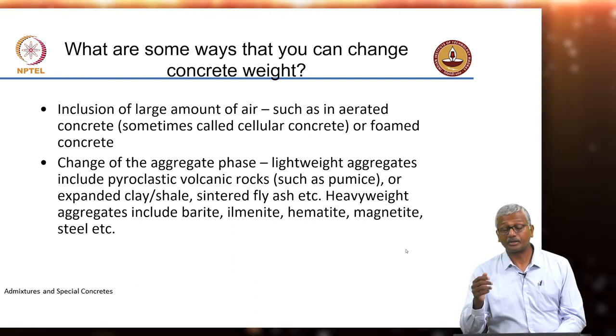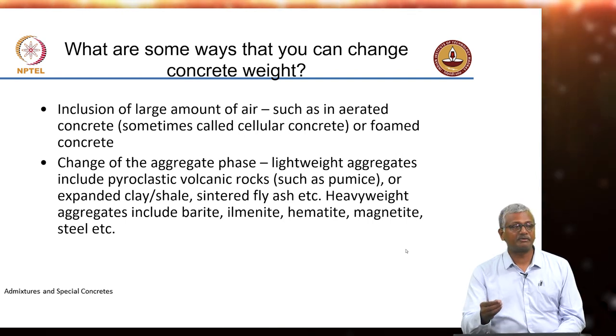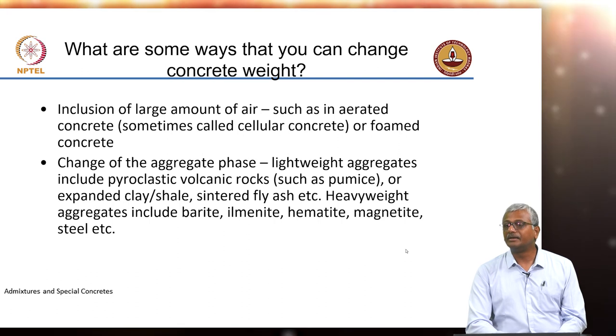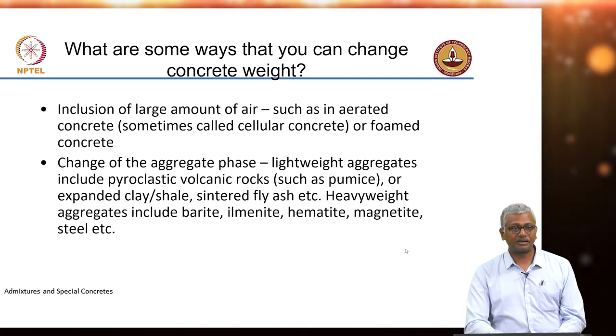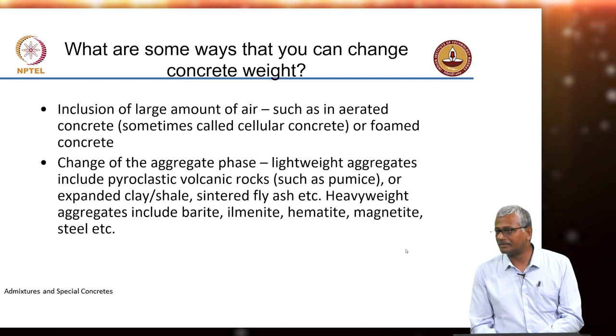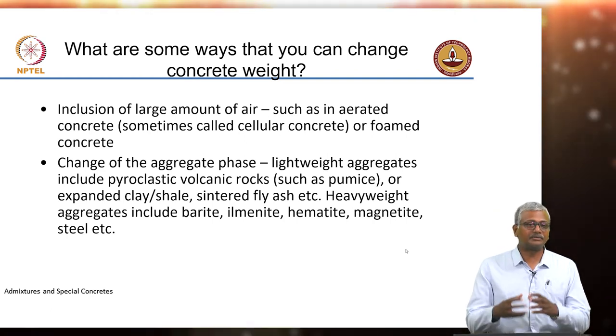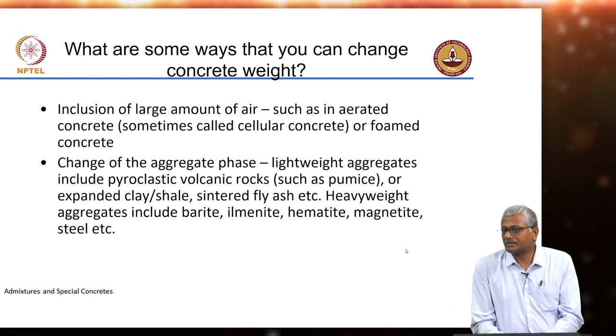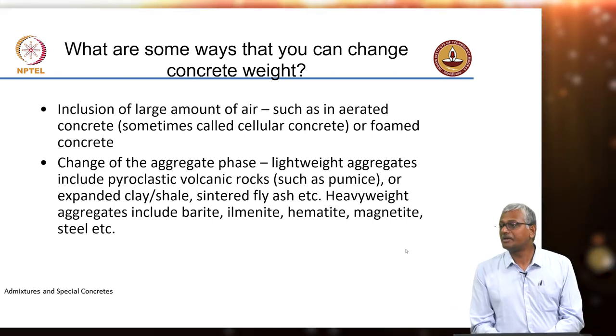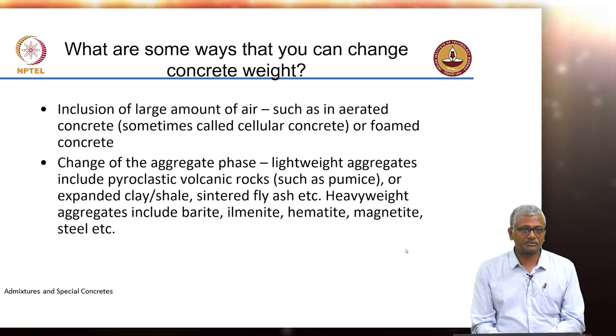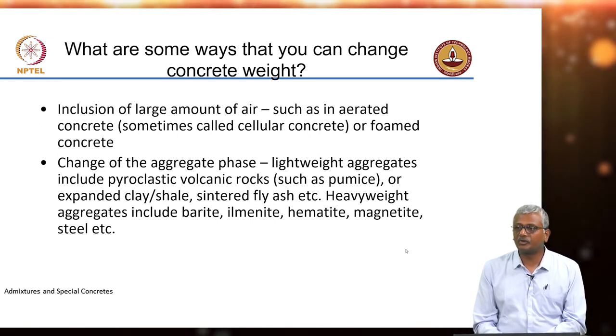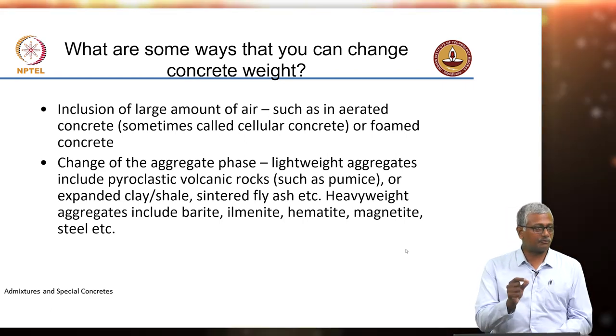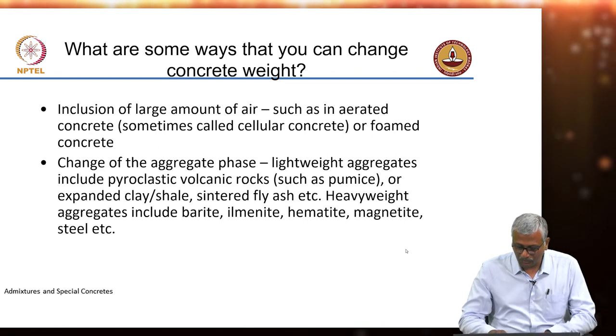Heavyweight aggregates are essentially those which contain iron, mostly like barite — which is barium sulphate and is also heavy weight — and ilmenite, hematite, magnetite, and similar iron-bearing minerals. Steel can also be used as an aggregate: you take a reinforcing bar, cut it into aggregate size, and put it into concrete — it becomes a heavyweight aggregate. If you want extremely high densities, they use steel, called steel punchings, which is essentially cutting reinforcement to the size of aggregate.